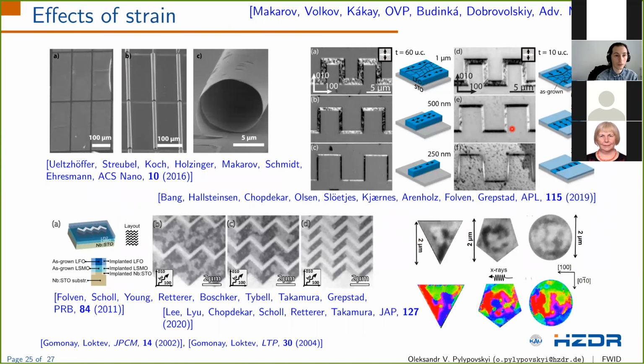Strain engineering is a well-established technique to transform initially planar structures into tubular devices. It is widely used for non-magnetic and ferromagnetic multilayers. For ferromagnets, this allows one to transform the perpendicular axis of anisotropy into the radial one, for example. Of course, it's possible to roll up exchange-biased and antiferromagnetic films. However, this is yet to be explored. In the absence of well-pronounced magnetostatics, antiferromagnets possess its counterpart, magnetostriction. And it acts in a similar non-local way on the easy-plane antiferromagnetic textures and leads to domain formation, which was partially discussed by Elena today.